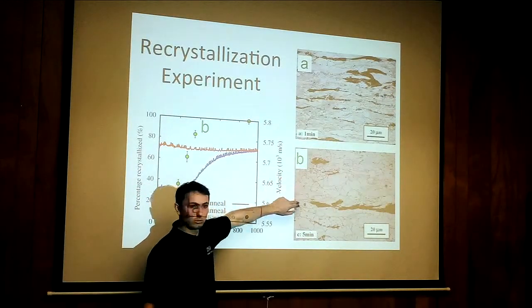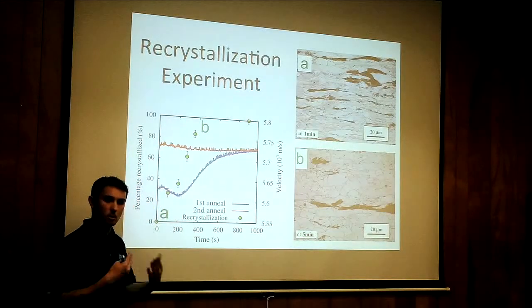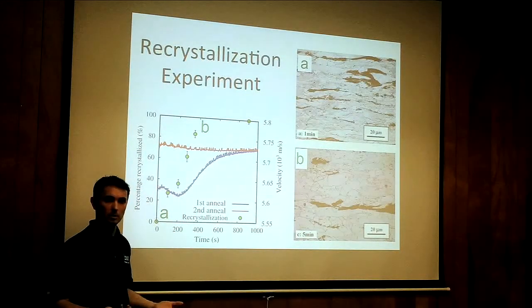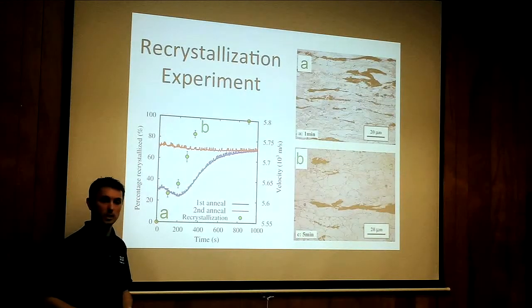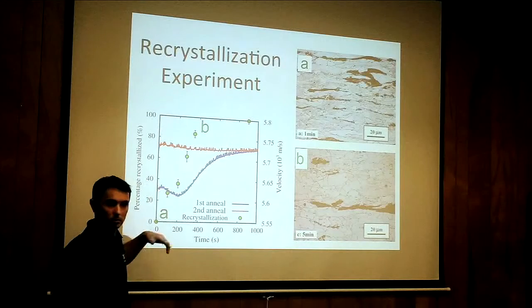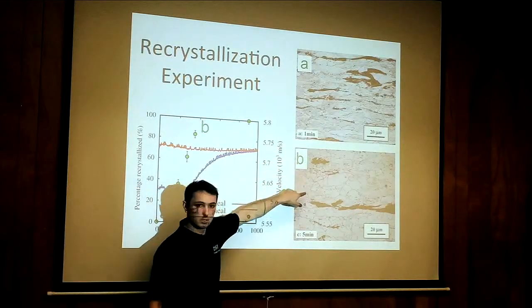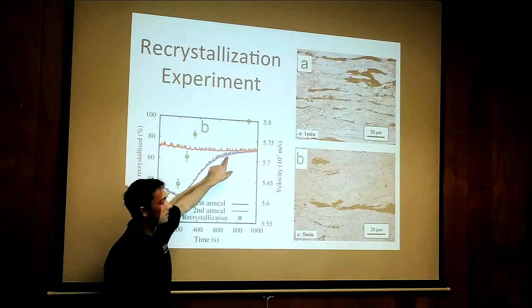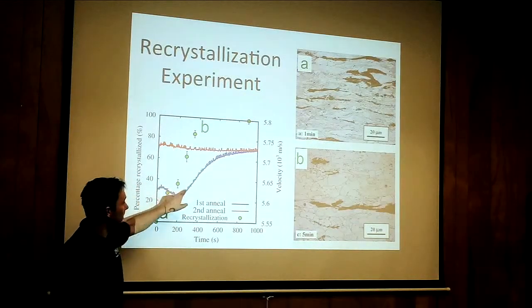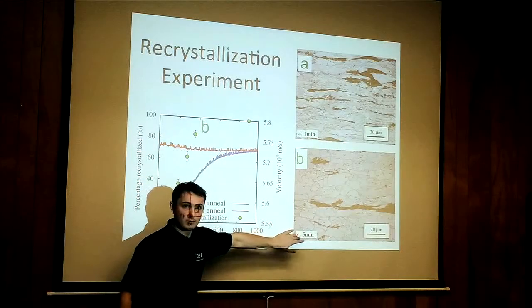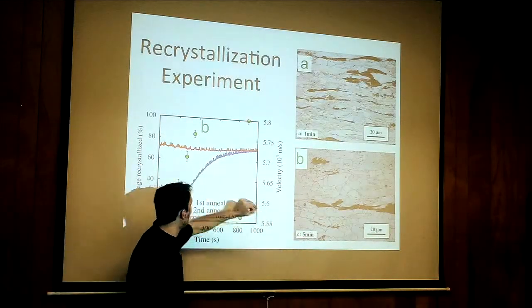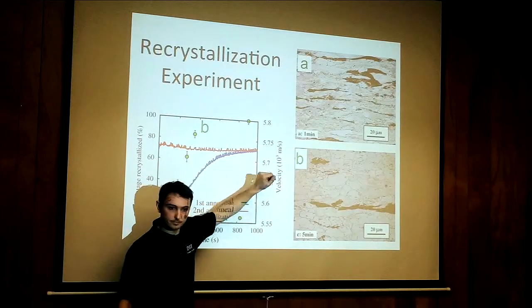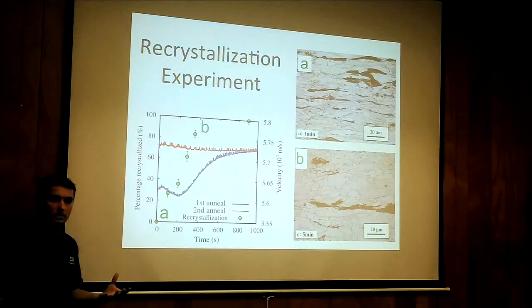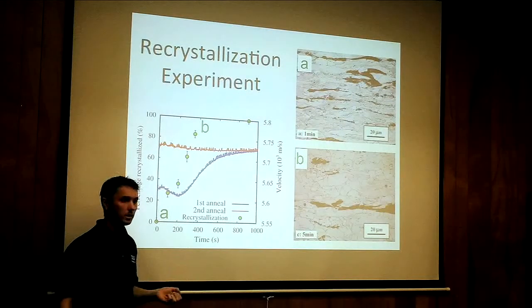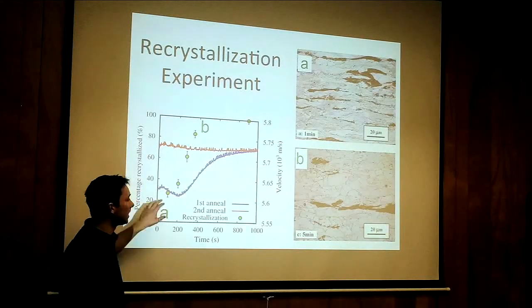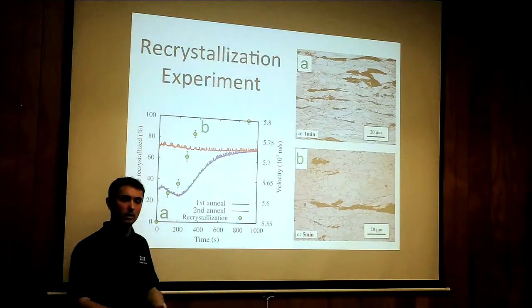This transition from this structure to this structure will be associated to an important variation in the bulk elastic property of the material. And so of course, because LUMET can capture those changes, we can see here during a first annealing, as the structure changed from this state to this state, an important variation in this velocity value here in blue. And then when we would take this structure and re-anneal it, nothing will happen in this structure, and we prove that nothing happened in this structure. So here again, this is a technique that can capture in real time and very, very quickly the entire kinetic of this recrystallization process.